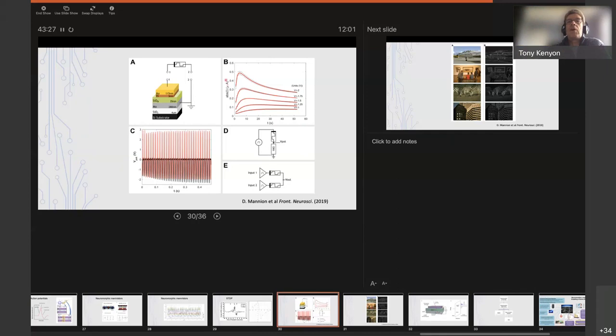This is a plot of current flowing through our devices as a function of time. What we've done here is we've initially stressed the device, in this case with a constant current, then removed that current, applied the voltage, and we see this. We see an increase initially of the current and then a decrease. And the shape of this transient behavior depends on the voltage that we apply.